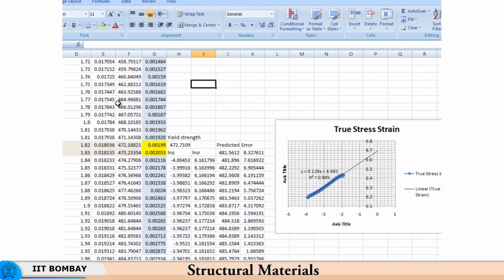So, I plot ln sigma versus ln epsilon, because I want to fit the plastic deformation curve into a constitutive equation sigma equal to k epsilon to the power n. This is the kind of Hollomon equation. So, k is the strength coefficient, n is the strain hardening exponent. So, k epsilon to the power n is my formula in which I try to fit it. So, ln sigma equal to ln k plus n ln epsilon, that is what I get as the equation. And I then use this to calculate the value of n and k.